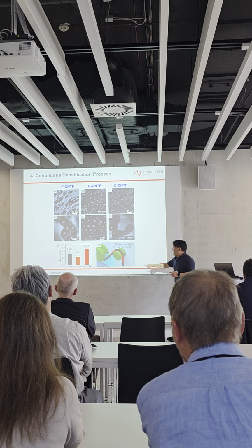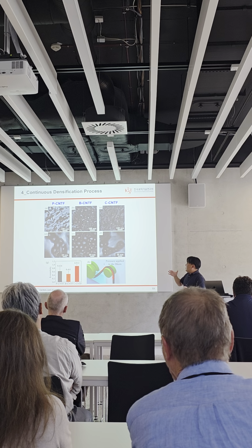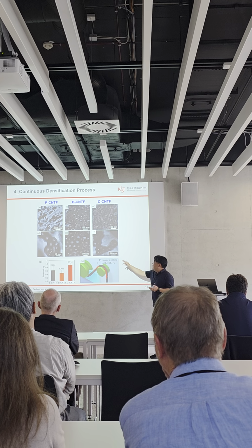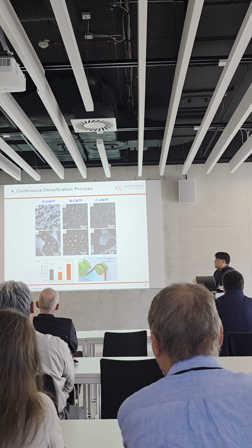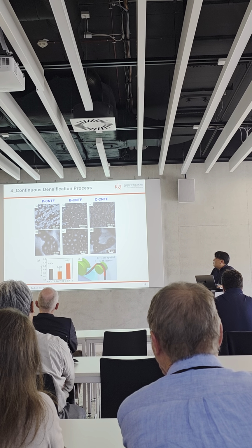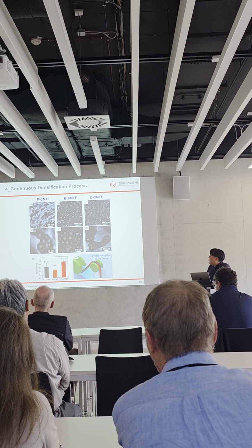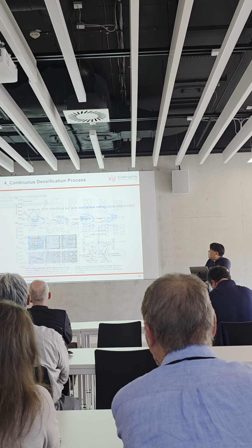It seems this pressure flattens the CNT fiber and also changes the shape of the CNTs composing it. This may be the possible reason why the properties of the continuously treated CNT fiber are higher than the batch process.